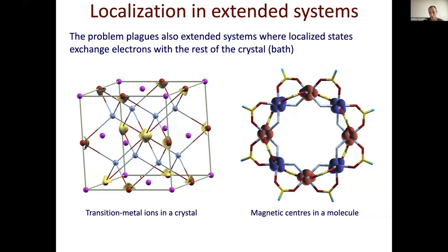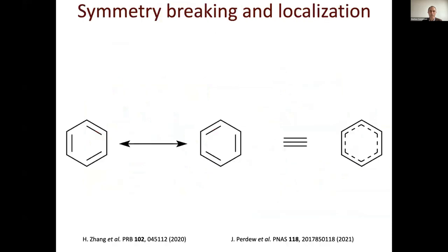And that can lead to significant errors, like I showed before, also for the magnetic properties. For example, underestimation of localized magnetic moments, or overestimation of magnetic interaction between sites, are the typical consequence of this over-delocalization of d or f electrons over the unit cell.